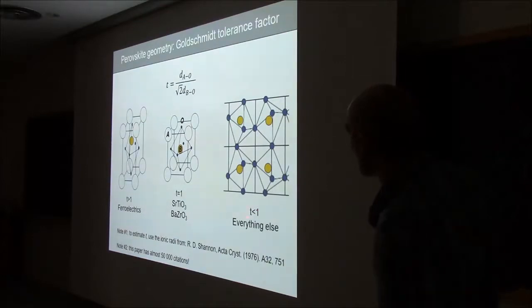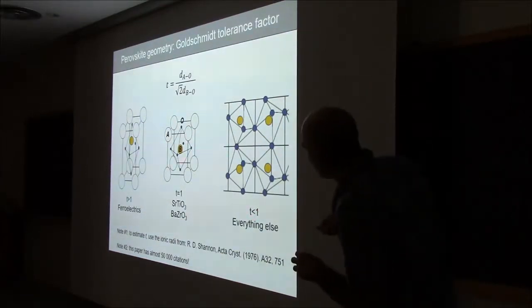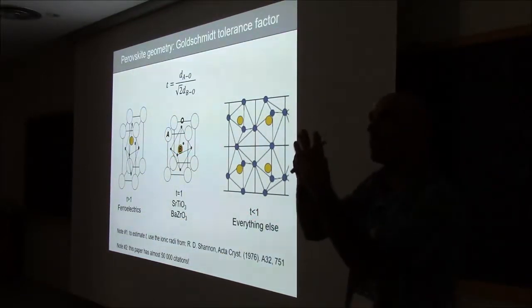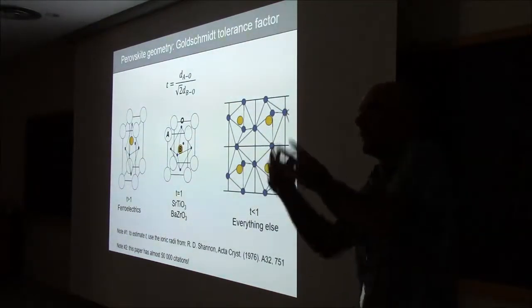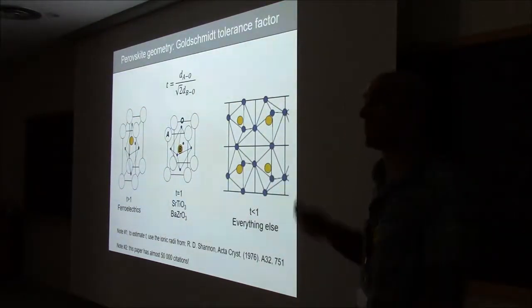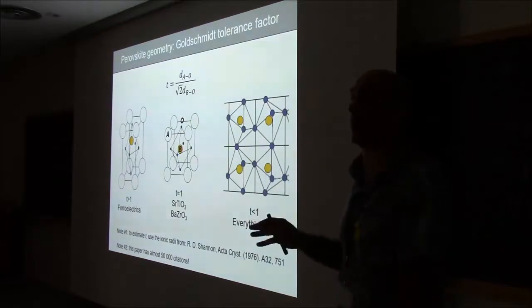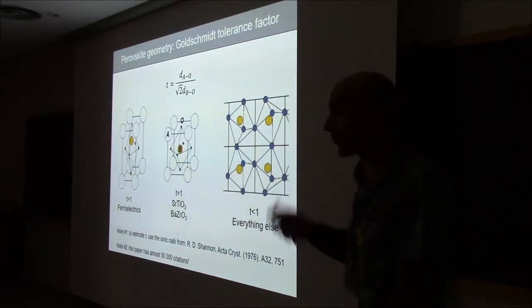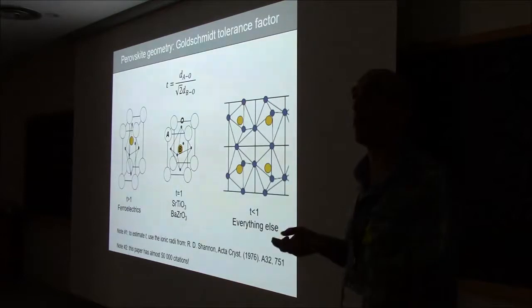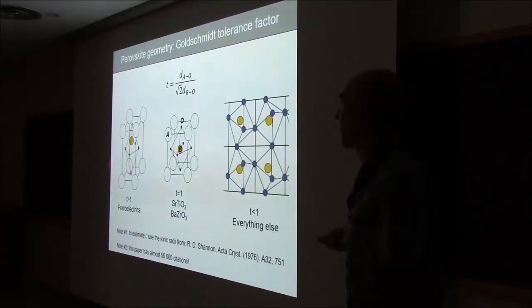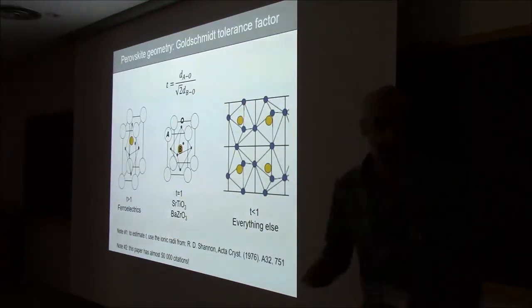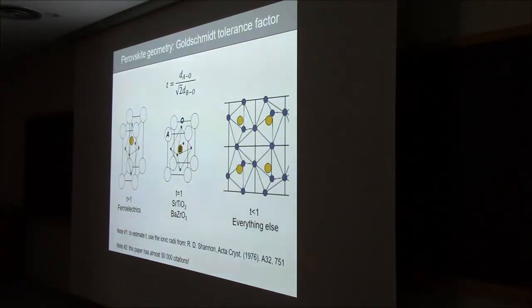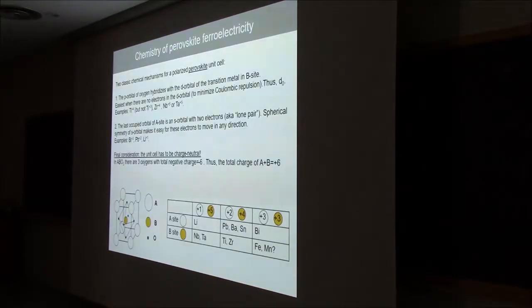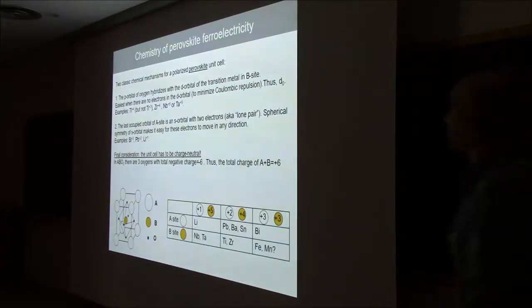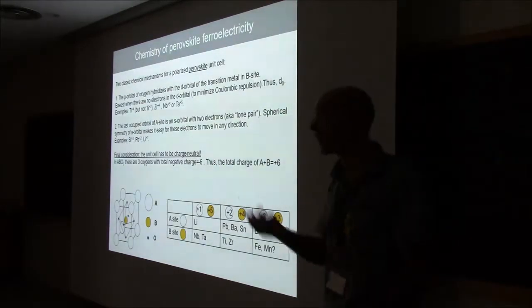And if t is smaller than 1, then this cage is too small, the octahedron doesn't fit, and in order to fit it has to rotate and tilt. Okay? And this in fact is by far the most common thing in perovskites. Most perovskites at room temperature are tilted octahedral systems rather than ferroelectrics or cubic. Okay? So that's the first consideration, pure geometry. And that can take you so far. Then there's a couple more considerations to do with chemistry.